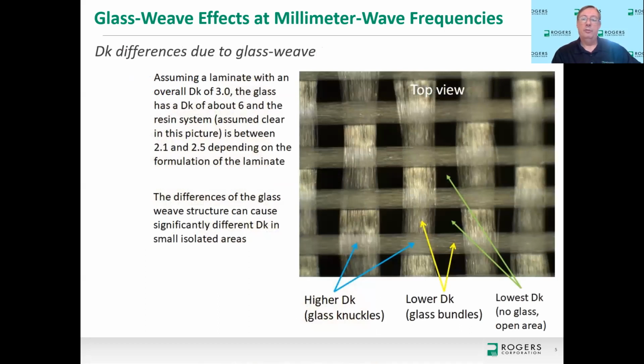Now, zooming in a little bit closer to one of these open weave glass and talking about the Dk difference. If the formulation of the laminate is intended to have an overall Dk of 3.0 and it is glass reinforced, the glass itself is about a Dk of 6. Which means the resin system must be much lower than that. So the resin system is usually around 2.1 to 2.5, and that depends on the glass to resin ratio and other things. But anyway, the main point is the glass is a much higher Dk than the resin system.